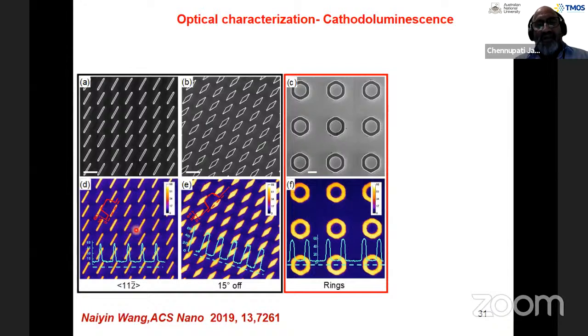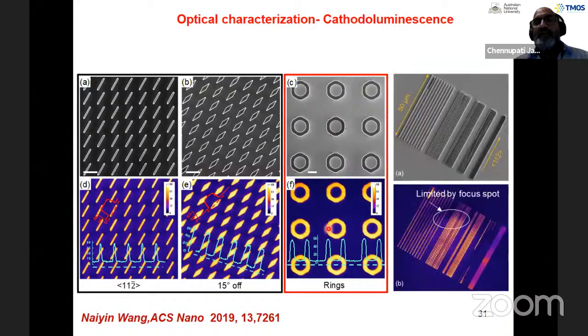You can see you get a very uniform light emission from these nanomembranes, nanodiamonds and nanorings, indicating that Naiyin Wang is able to get excellent quality nanorings and nanostructures with no defects. If there are defects, you end up getting a non-uniform light emission. The uniform light emission is a good indication that we managed to get very good structures. So now, in fact, we're using these nanorings, for example, as ring resonator lasers. In fact, a new student, Wei Wong, who started a PhD a couple of years back, has recently demonstrated ring resonator lasers, which I will not have time to talk about.